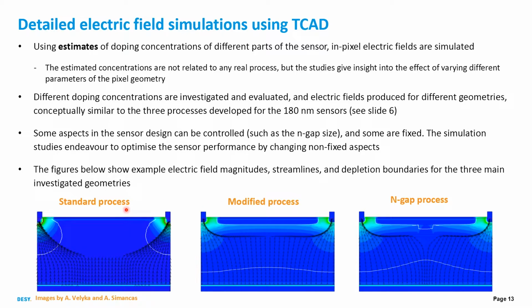And these 3 figures show example electric field magnitudes and streamlines and depletion boundaries for the 3 main geometries, so standard process, modified process, n-gap process again. So streamlines are these black lines, so electrons will travel along the streamlines. The color corresponds to the electric field magnitude, and these white lines are the depletion boundaries. So in the standard process, you see the depletion is just around the collection electrode, basically, whereas in the modified and n-gap, they're basically fully depleted. Now, in the undepleted regions, movement is primarily by diffusion, so the streamlines don't matter all that much, but when we come here, streamlines matter more in the electric field.